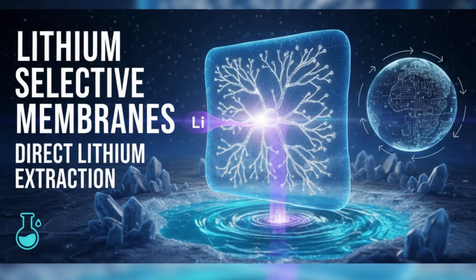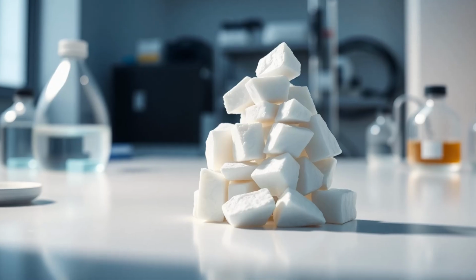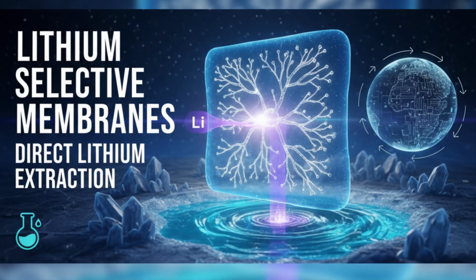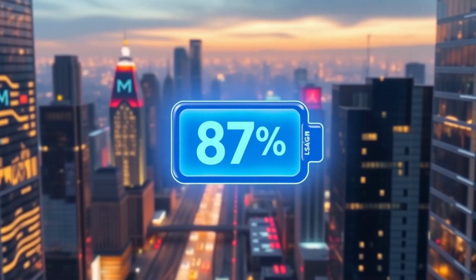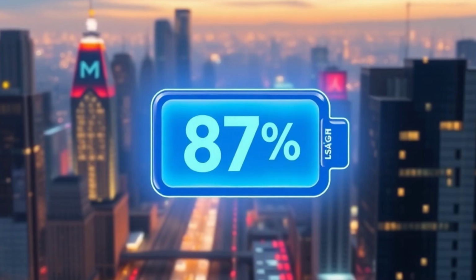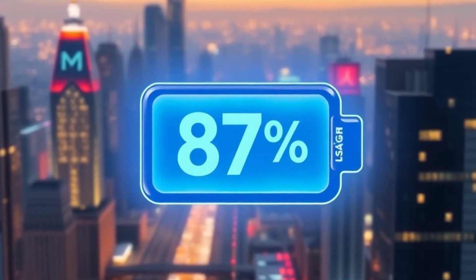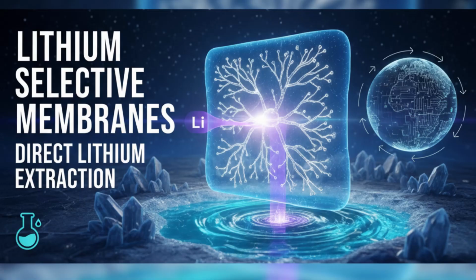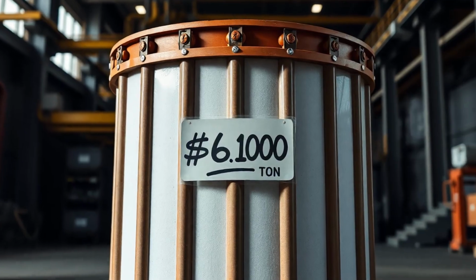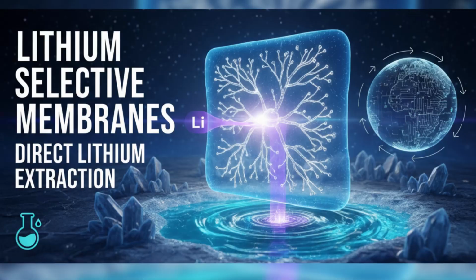Today, we're diving into, well, arguably the core of future energy storage. We're talking lithium, sometimes called the white oil. It's a fitting nickname, definitely. I mean, the growth it's fueling is just exponential. For lithium batteries alone, lithium use hit an estimated 87% of total consumption in 2024. Wow, 87%. And that demand sent prices soaring. Yeah. You look at 2022, the average for battery-grade lithium carbonate was $68,100 per ton. 68,000. Almost 6 times the price of just the year before, 2021.